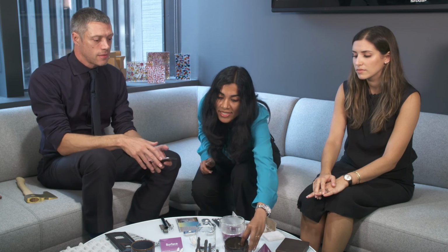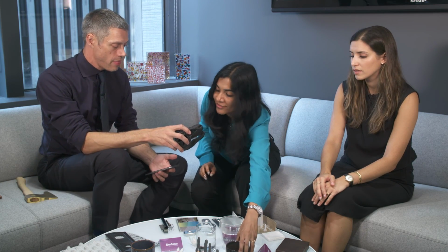Okay. And I think there's a follow-up question to the same one. Is there a weakness at the printed layers junction? So as you put down each individual layer, is there a weakness there? Actually, there is no weakness in that case. Yeah, I'm talking about the carbon fiber. Oh, yes, okay. Sure. So as they print the individual layers, they're asking because you've got a fiber layer and then you're sticking another layer on top, and you don't get bonding between the fibers of the two, are you getting a reduction in that strength? I don't necessarily think we get any kind of reduction in the strength in the vertical direction just because you're having layer by layer assembly.